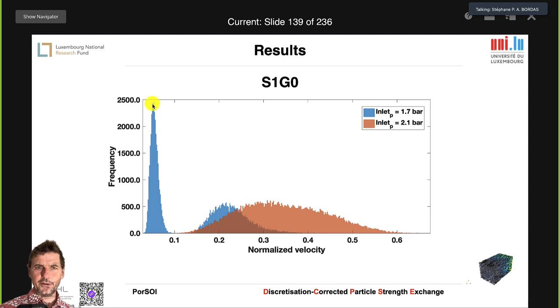instances of this value. So we have 2,500 points in the system which see this velocity, right? So we have a lot of points, over 2,000, which are beyond this velocity of about 0.05. On the other hand, if we take 0.6 in terms of velocity, we see there is almost no pore that has a velocity of 0.6.